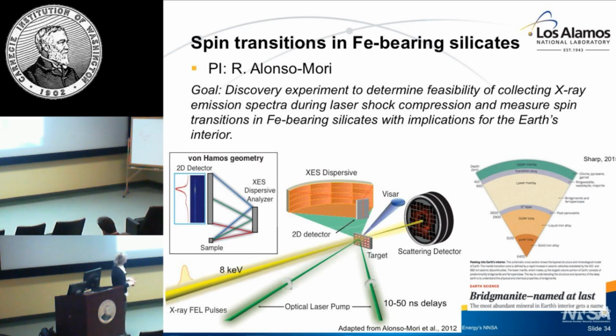We endeavored on an attempt to explore electronic transition in an iron-bearing silicate, in this case an iron-bearing pyroxene, and structural transition. So can we divorce the onset of these two transitions, and what implications might that have for the Earth's mantle? Again, it's a pump-probe technique, so we have our target in the middle. Our drive laser comes in on one side. Our X-ray free electron laser, this time in yellow. We do collect diffraction, so we have structural information, but now we also have a spectrometer, okay? And we're going to utilize X-ray emission spectroscopy.